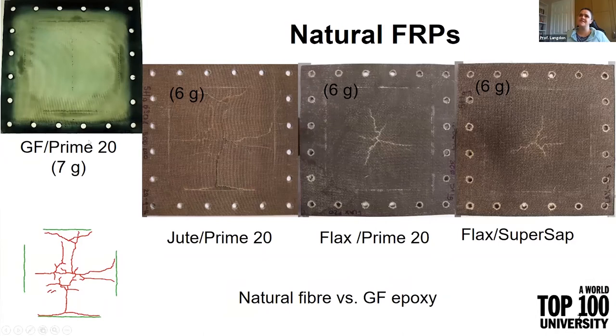And on the left-hand side, the greenish image is glass fibre Prime 20, which is a marine grade epoxy resin, subjected to a 7 gram charge. So this is essentially equivalent conditions, except the glass fiber is a slightly higher charge mass. You can see the whitened areas on the panels, those are cracks, extensive cracks. And in the bottom left-hand corner, you can see green and red lines. That is the mapping of the cracks on the rear surface for the Prime 20 panel seen on the screen. So we can take these crack patterns and measure them and look at how they change with charge masses to get some idea of what's going on in the materials.